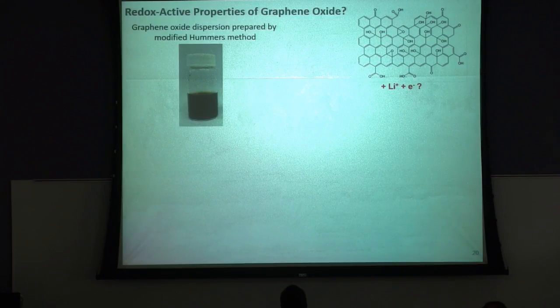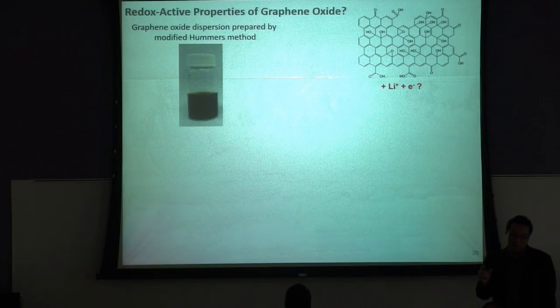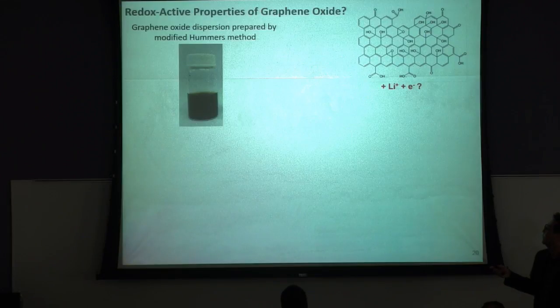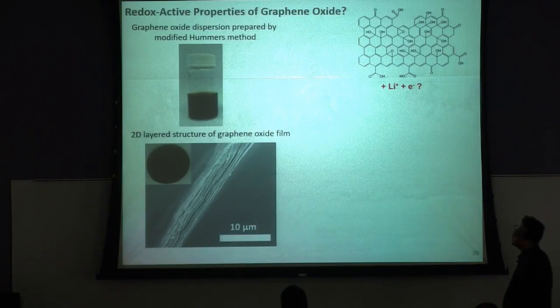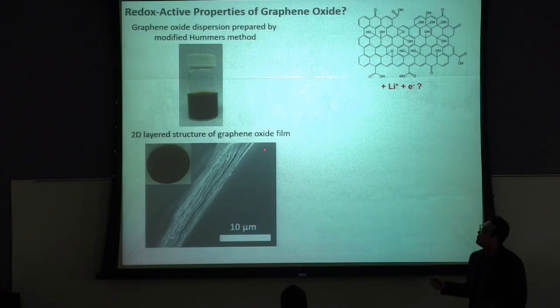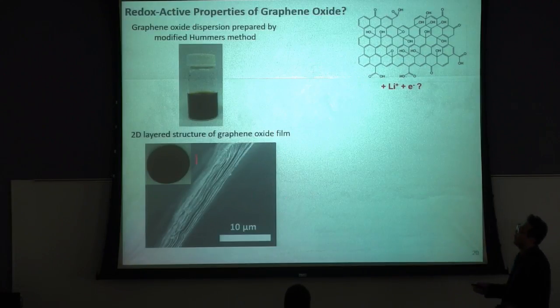The question is, can we have this kind of surface redox reaction with the oxygen functional group on the graphene? And the second question, if yes, how can we effectively utilize this kind of redox reaction? So to answer these questions, we prepared graphene oxide film using the vacuum filtration method. We just vacuum filter this graphene oxide solution so that we can get this kind of graphene oxide paper on top of the membrane, and we can detach this paper from the membrane. So then you can see this kind of 2D layered structure of the graphene oxide film.